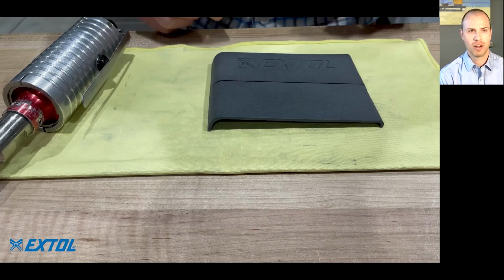The reason it's a little bit gray on the outside is because that's the boundary layer between the white powder that was not fused and the black fused part on the inside. So when we're welding it, like the extrusion welding, we're using a black rod. So that's simply why it is.